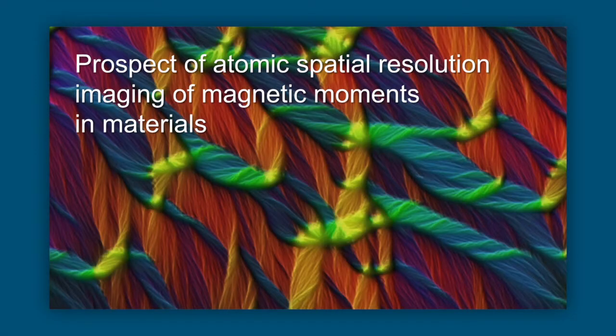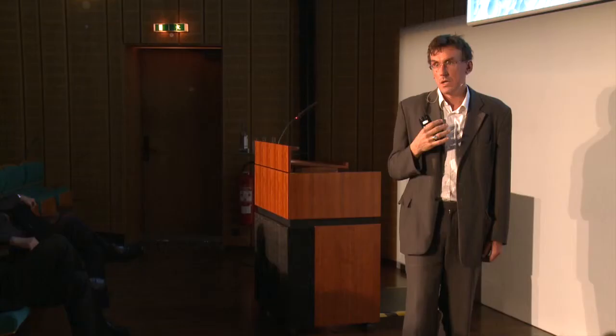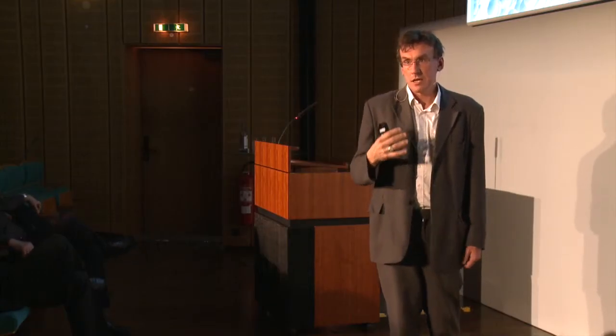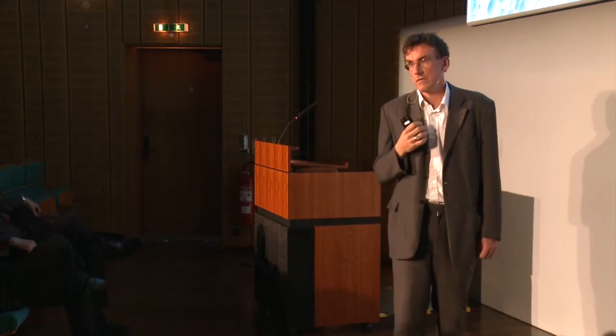This information is important for a number of reasons. Magnetic crystals are used across all scientific disciplines — physics, chemistry, biology, and engineering — and in applications ranging from drug delivery in medicine to magnetic recording, magnetic sensing, and catalysis. It is also important to study how defects, surfaces, and interfaces affect magnetic microstructure, as the relationship between local crystallography, chemistry, and magnetic microstructure is still not understood on an atomic scale. Chromatic aberration correction is necessary here because magnetic materials are usually imaged with the objective lens switched off, and even with spherical aberration correction, the non-immersion lens still suffers from chromatic aberrations.